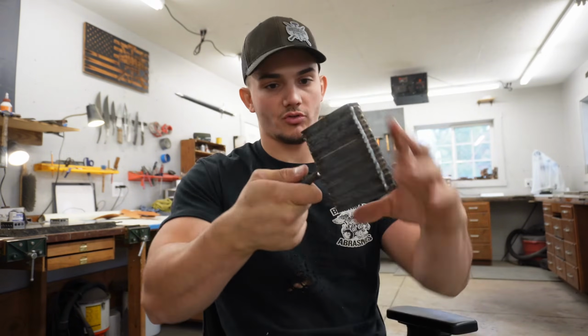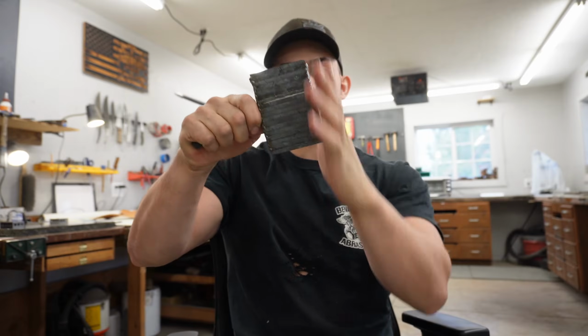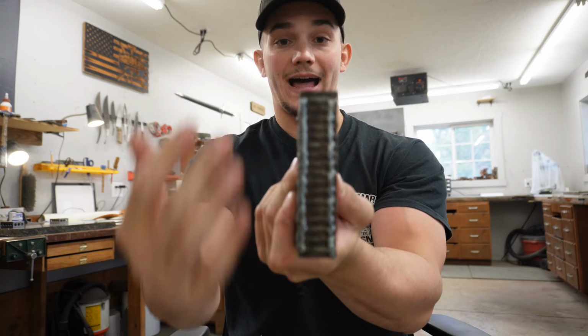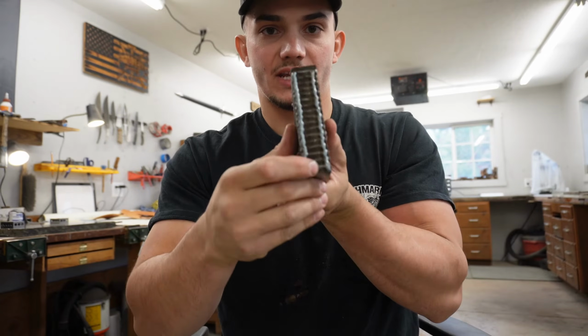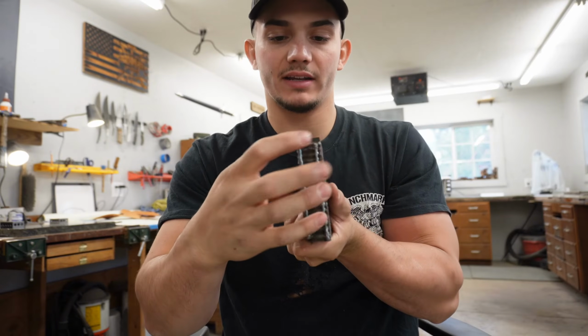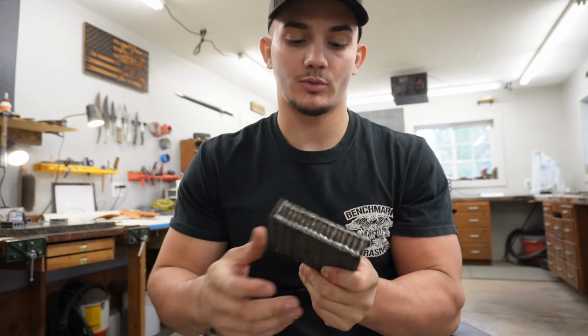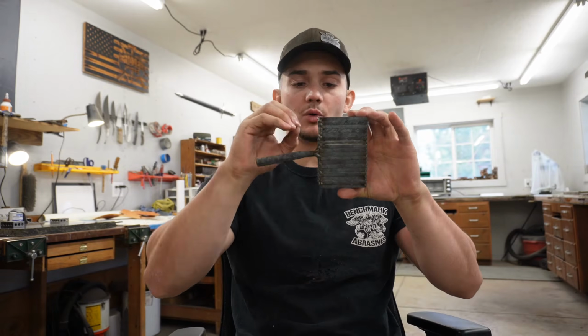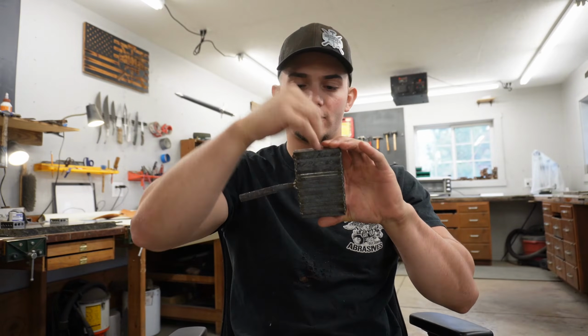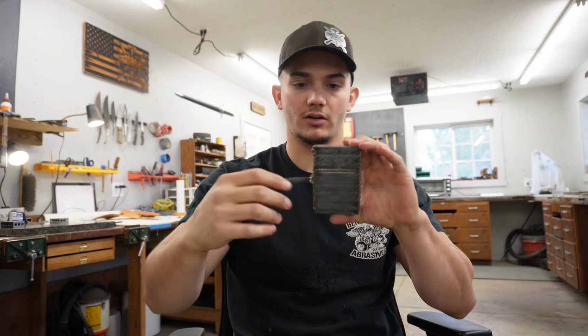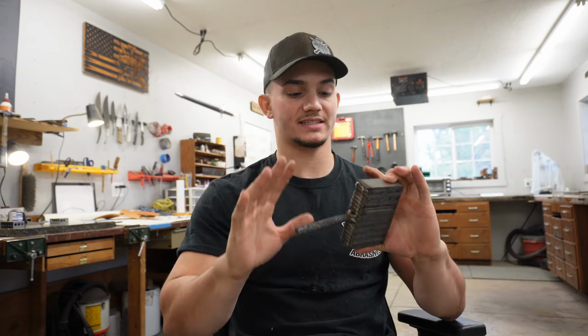feather it. But before you do any feather, a few things need to be done. I've already done one of them, which is grind the sides completely flat and flush, and then weld a ladder, is what I call it. So you have each seam horizontally welded, and then you have these ones stretching this way. And this is because when you're feathering the billet, it wants to split at the ends because there's so much pressure being pushed into the steel. So having these welds there and having it completely flush is gonna allow those forge welds to stick very solidly